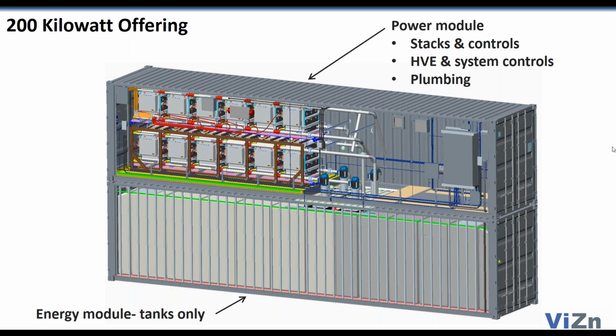Those are good questions. The system was specifically designed for maintenance. If you look at this diagram, you can see in the middle there's 4 little pillars with blue caps on them. Those are the pumps. Those can simply be lifted out and taken out the right end of the container as you're looking at it. The battery stacks that are in there, there is a service aisleway that can be walked along. All contactors, fuses, electronics boxes, wiring can all be accessed from inside the container by walking down the side. In the rare event that you have to remove and replace a stack, the stack is on a sliding rail and it can be essentially slid out the left end of that container and picked off that rail with a forklift and replaced, and the new stack slid back in. Everything else can be accessed inside the container in the workspace and aisleway.